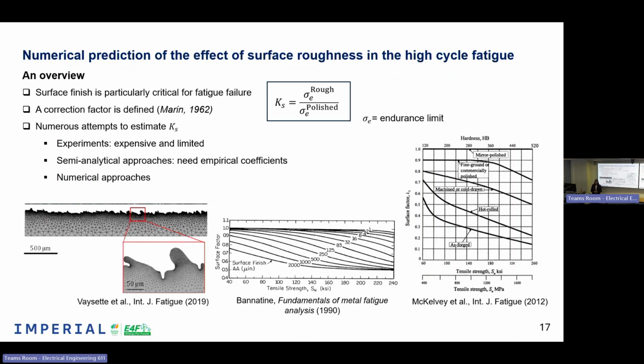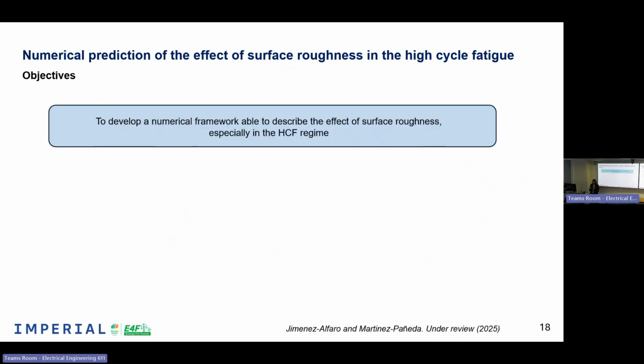That's why there were also numerical approaches, and most of these numerical approaches were based on going to the lab, making some surface roughness in the specimen, then using any kind of technique, for example, scanning electron microscopy, to measure this surface roughness, and then they import the surface roughness into the computer to build the mesh. Once they have the mesh, they apply any kind of methodology to get fracture. One of the problems of doing so is that we again need a lab because we need to make the specimens, then we need a very good measurement technology to get the microstructure, and finally we need to come back to the computer, which is a long process because we need to touch everything.